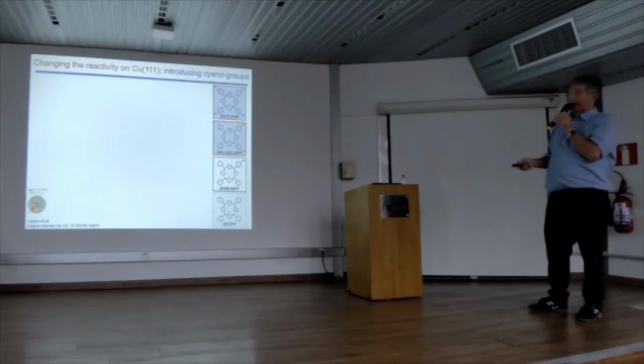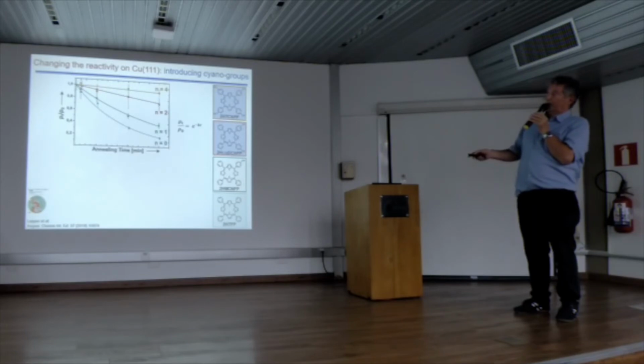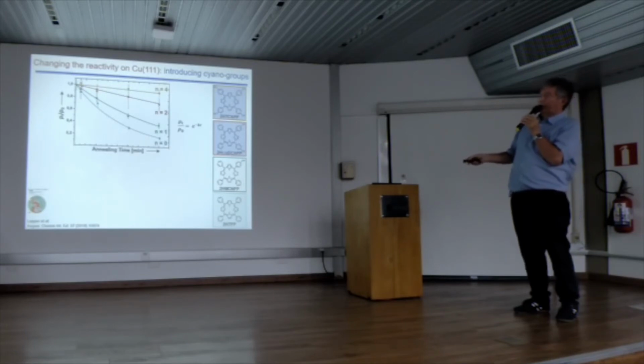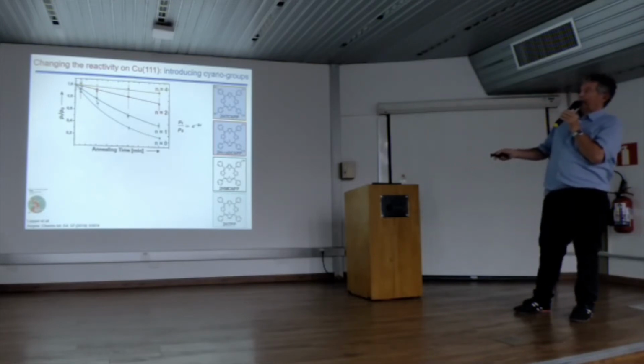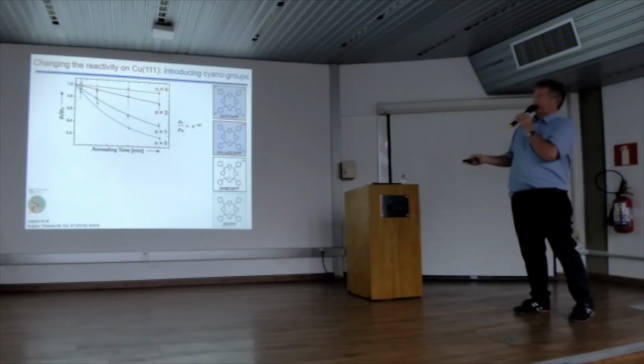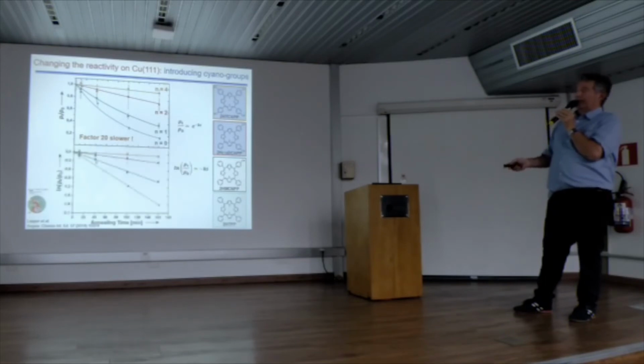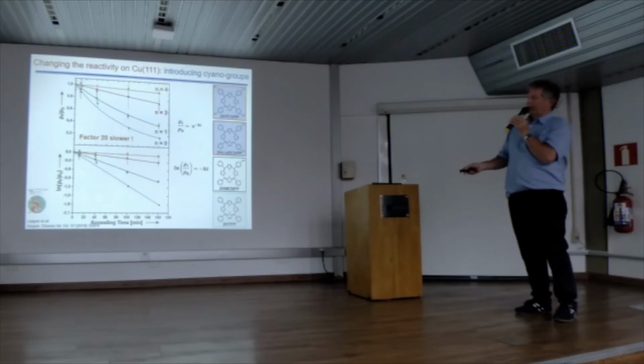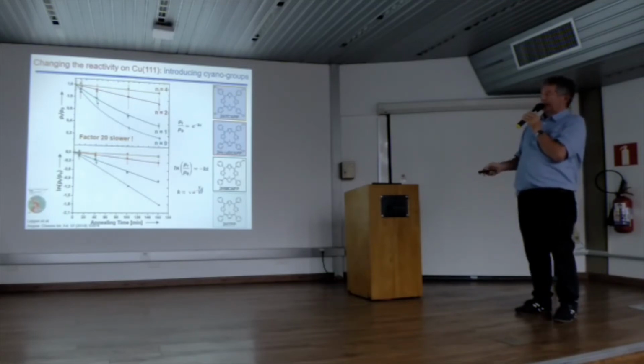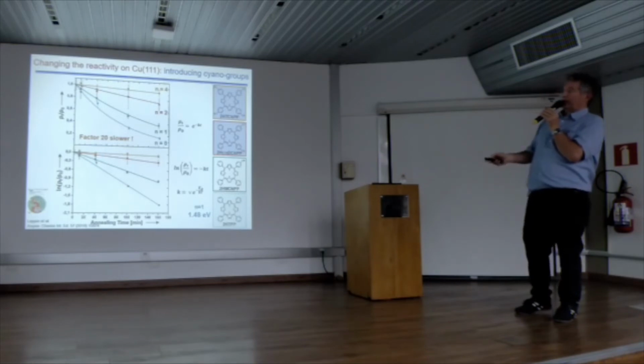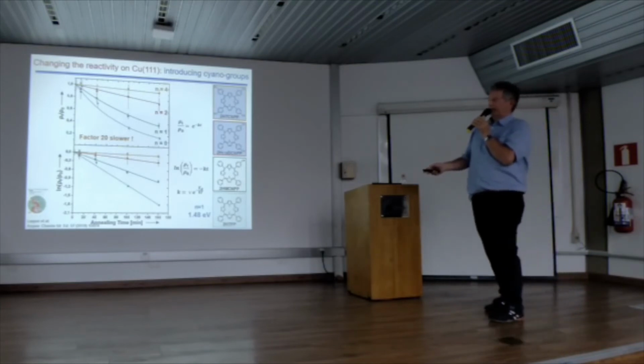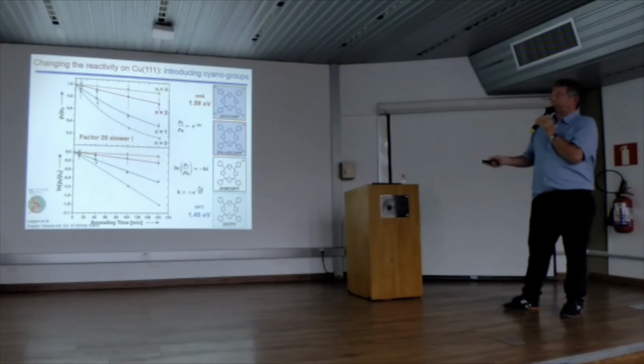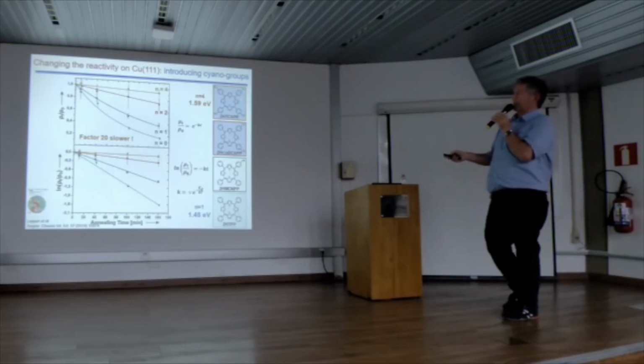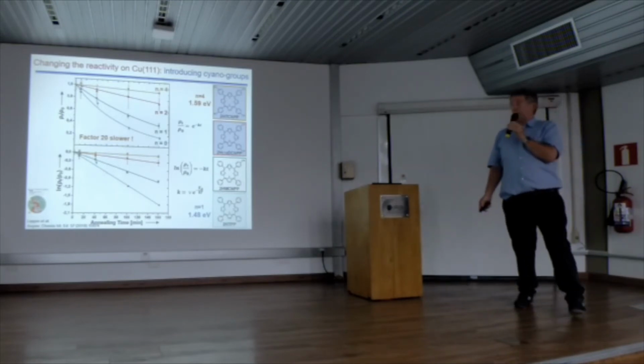And then we studied the decay of the density on the surface. This blue curve is what we have seen already with the activation energy of 1.49. And you see, as we add 1, 2, and 4 cyano groups, the reaction gets much slower, a factor of 20 slower. And we can also plot these curves again on the logarithmic scale, as we have seen before. The slope here is steep, the slope here is flat, and if we use the Arrhenius equation and assume that the prefactor is the same, then we know that here is the activation energy 1.48 eV, and then we can calculate the activation energy that is necessary to get the reduction of the reaction rate by a factor of 20. This is 1.59 electron volt. So by introducing these groups here, we can modify the reaction rate as we want.